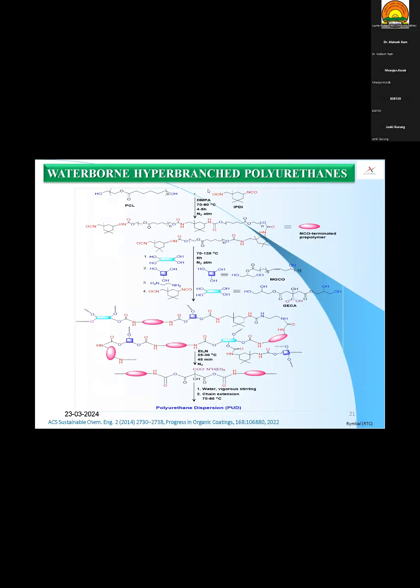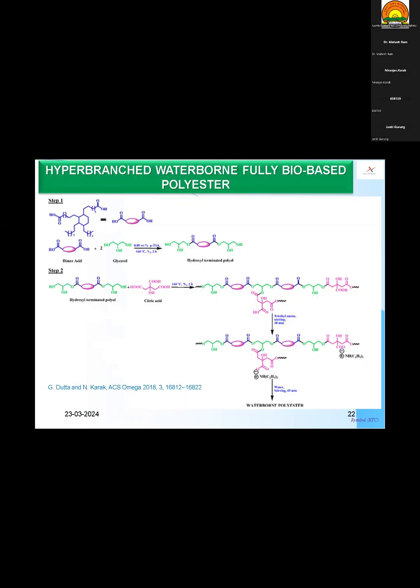We have also synthesized a different type of waterborne polyurethane system, polyurethane dispersion, using a bio-based system again, and without any gel formation, we can get this hyperbranched polyurethane structure. However, with this kind of system, you have always seen that some petroleum raw materials are used. So our latest research was how to get a fully bio-based hyperbranched waterborne polymer system.